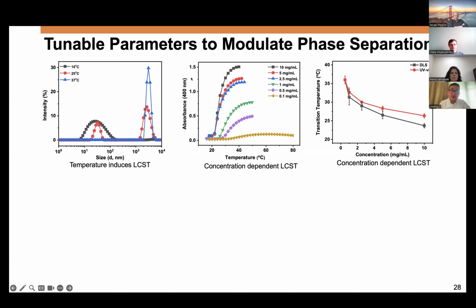We also used UV-vis turbidity assays, looking at the absorbance at 400 nanometers, and we also did a concentration range. You can see this is really concentration dependent. As you increase the concentration, you lower the transition temperature, where we use the onset as indicating the solution becomes cloudy. Then we overlaid the UV-vis and DLS to show the transition temperature. We see slight differences at the high concentration, but in general a good trend: as you increase the concentration, you lower the transition temperature.